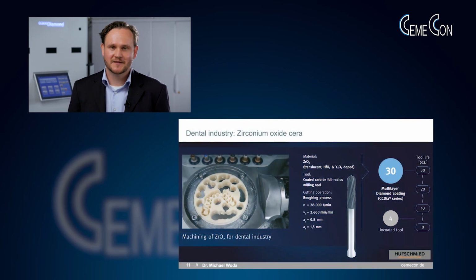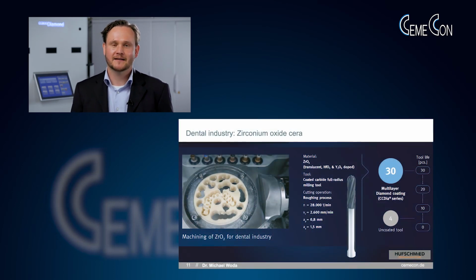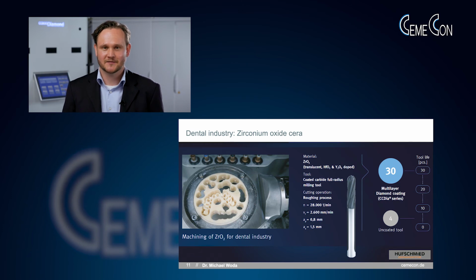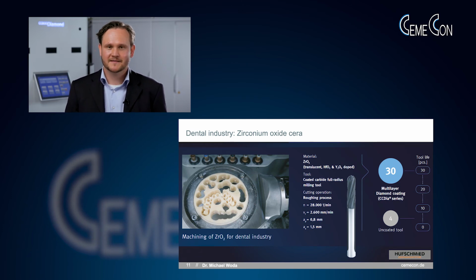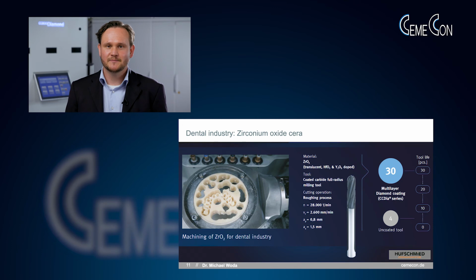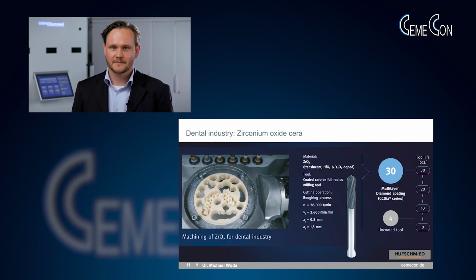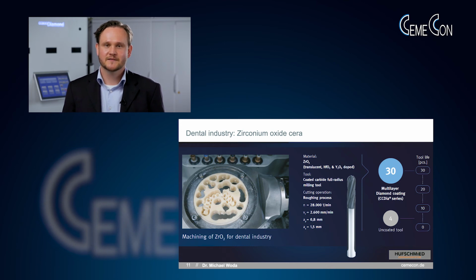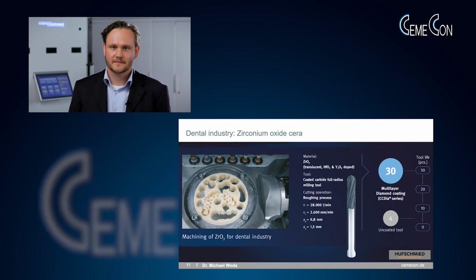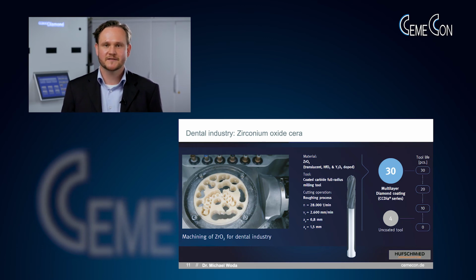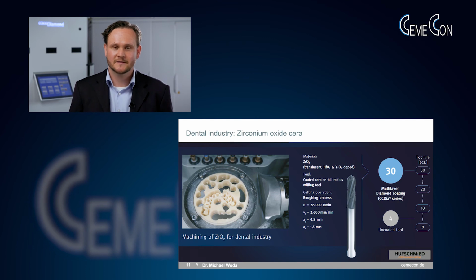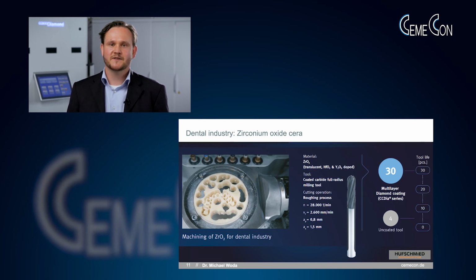Next, after lightweight materials and graphite, we are here looking at an example in the medical sector. Nowadays, tabletop and on-site milling devices have become very popular at dentists to produce dental implants on a very short time scale. Here we are seeing a comparative study on milling translucent zirconium oxide material. Whereas the uncoated reference only has a tool life of 4 pieces per tool, the diamond coating reference shows an impressive 30 pieces per tool.